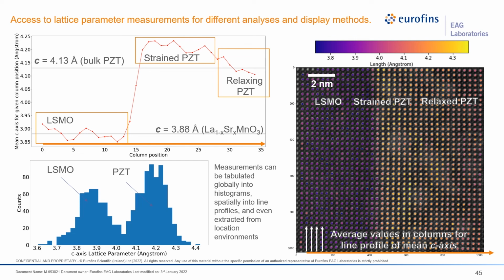So we can perform this kind of quantitative analysis from sample to sample and have a way to accurately compare samples over time. You can also plot the data more globally into histograms, et cetera, so there are different ways you can visualize this. You can also measure the out of plane strain as well, and things like that. Certainly there are issues with sample relaxation that must be taken into account, but ultimately through careful controls, you should be able to set up a situation where you can measure this kind of feature over time and get some valuable information out of it.